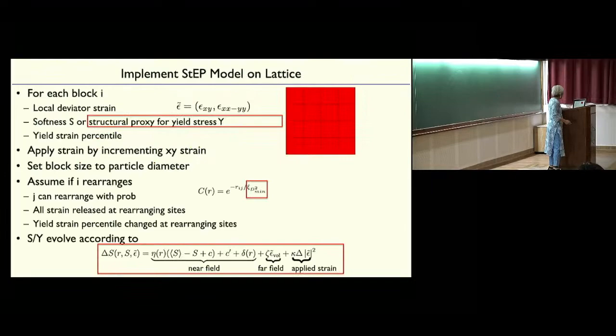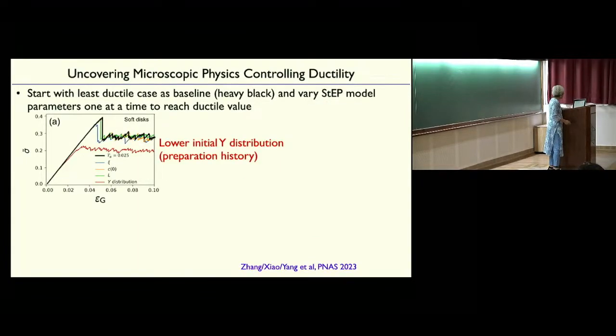All right, so what changed in these two cases? In the first case, the Monte Carlo swap systems, we took each of the parameters that changed from fitting the softness kernel and the elastic kernel, and we tuned them from the brittle case to the ductile value, one by one. And you see that the only thing that made a difference was the initial distribution of yield stresses, which is exactly the only thing that changed in the system. Everything else was the same. So it was the preparation history that changed.